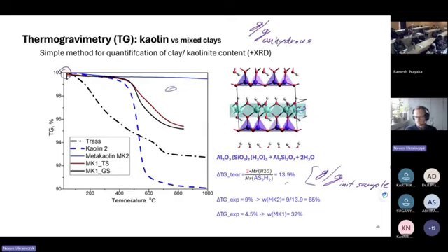You actually need to take the, you should divide or multiply. I don't know now, you figure out. You should just take the mass loss. Usually I took the mass loss at 1000. But actually, it's even better, in that book, they suggest mass loss at 600, I think, because then it depends. Do you want to include the carbonates or you don't want to include the carbonates? I don't like to include the carbonates. Now I forgot why they suggest 600.